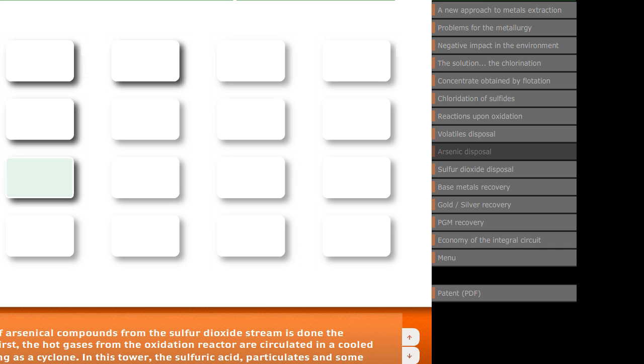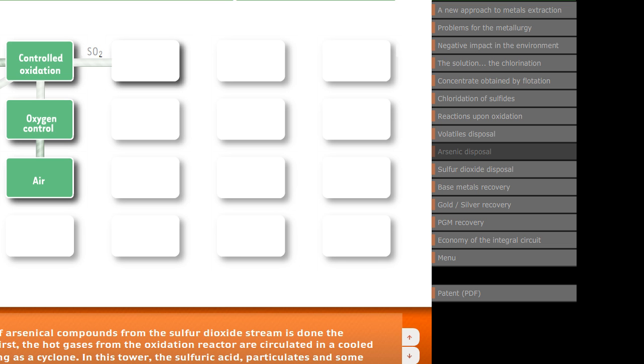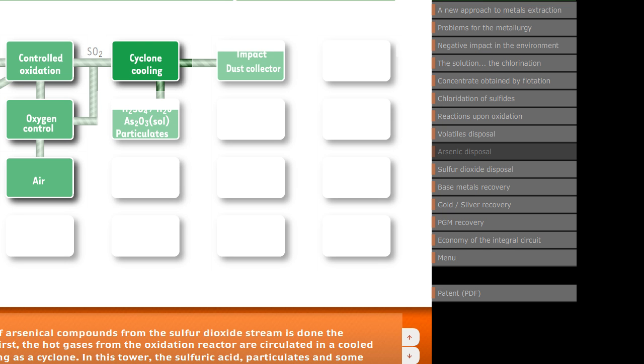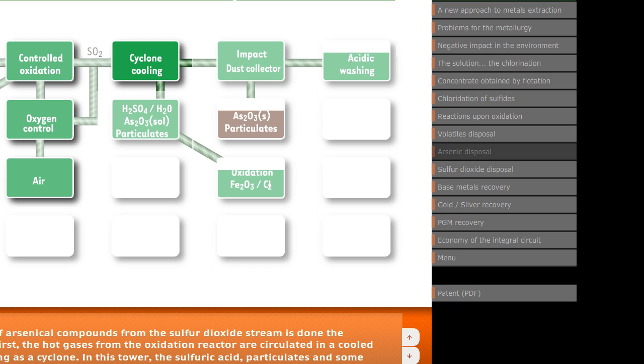Extraction of arsenical compounds from the sulfur dioxide stream is done the following way. First, the hot gases from the oxidation reactor are circulated in a cooling tower acting as a cyclone. In this tower, the sulfuric acid, particulates, and some arsenical vapors are condensed and washed out. These washings are oxidized by chlorine in the presence of iron to precipitate scorodite along with gypsum from neutralization by limestone.